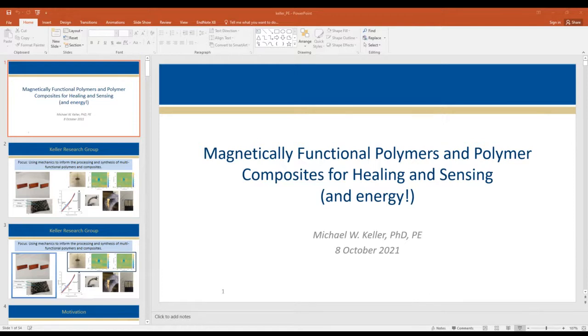We tried doing it in impact. This is kind of what it looks like in fabrication. What they did is they laid it up and sprinkled. It took them about two weeks of steady, like six or eight hours a day, running these flow focusing devices to get enough microcapsules to actually make a sample. Again, a lot of time. Then we did some impact. We did a single impact, saw some color change, and then did a couple more impacts to try to break things up. Unfortunately, I think we just didn't have enough concentration in this case.